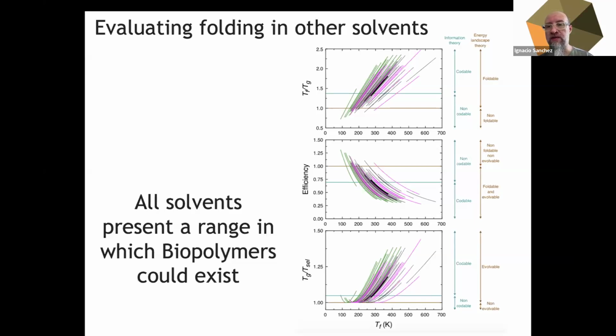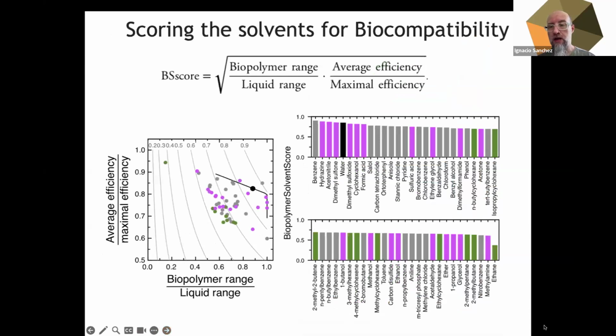The main conclusion here for all 54 solvents in our database is that all of them present a range in which biopolymers could exist. That is, they could fold and they could evolve. So many solvents are in principle suitable for life. Having said that, we tried to rank them. We defined a biopolymer solvent score. That's the geometric average between two things that seemed interesting to us. First, the normalized efficiency for conversion of folding free energy to sequence information. Second, the fraction of the liquid range that is apt for biopolymer folding and evolution.